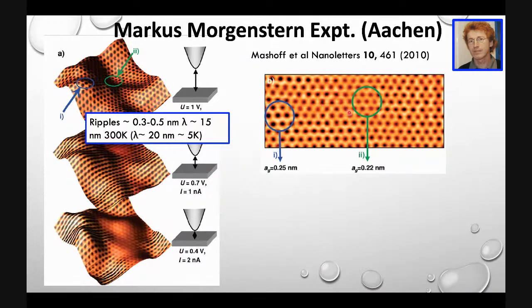And let me add that he saw practically perfect hexagons, and in this technique what you are seeing is the distribution of electronic charge. You expect to see hexagons because, if you remember, the lines that form the hexagons are representative of the distributions of electrons. They are equally shared by the two carbon atoms, so what you expect is that they are shared along these sigma bonds, this structure given by the sigma bonds that describe the graphene lattice directly.